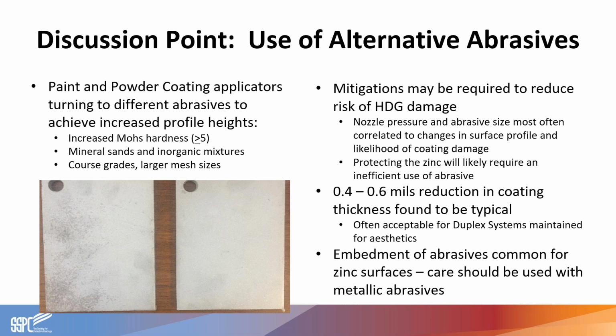Overall, the use of these products has been met with mixed success. And the reason for that is, you might hear someone say, oh, I had great success using garnet over galvanizing, and then someone else could have had a poor experience. The reason for that is without certain mitigations, it can be very easy for someone unfamiliar with hot dip galvanizing to damage the surface with these materials. Another issue is the blast media does not give the same surface roughness properties, such as peak height, when you are using them on a galvanized surface versus a bare steel surface. So you can't just take the spec sheet from an abrasive supplier and then apply that directly to a zinc coated surface.